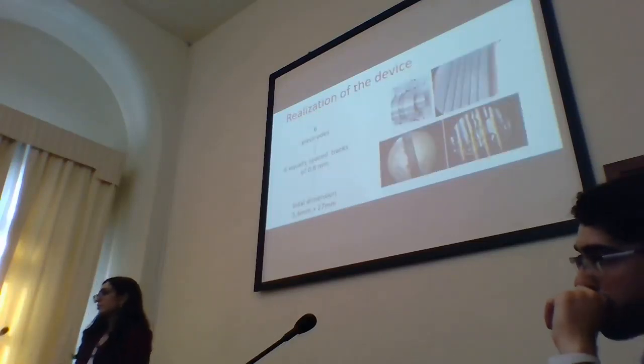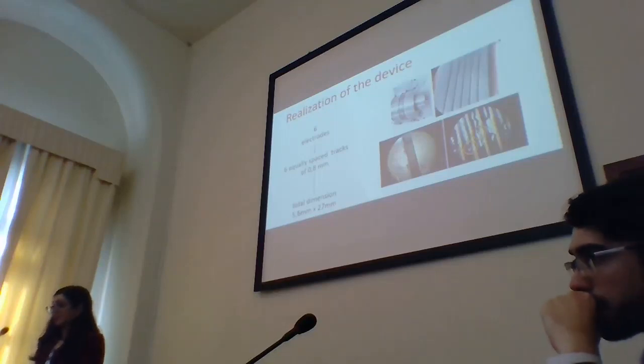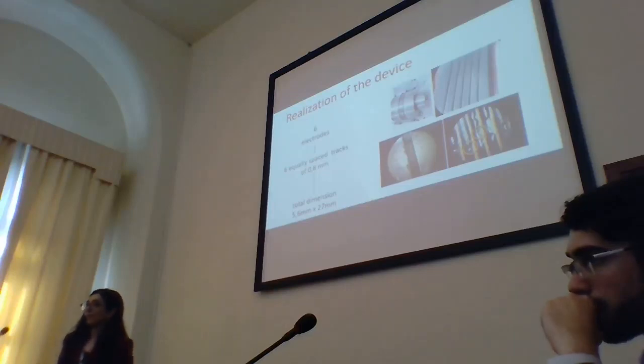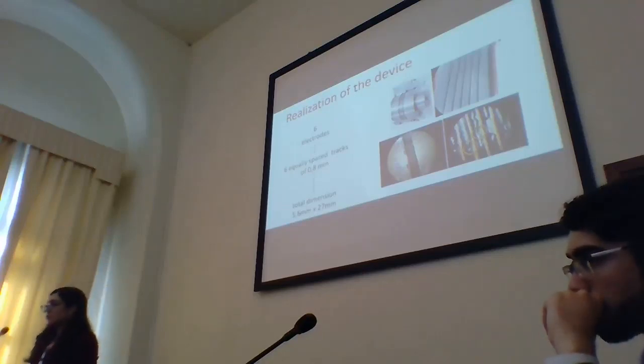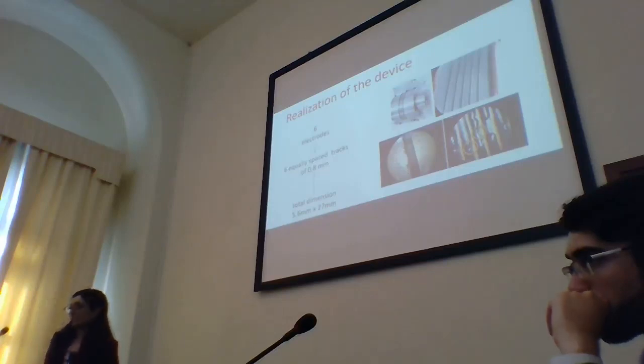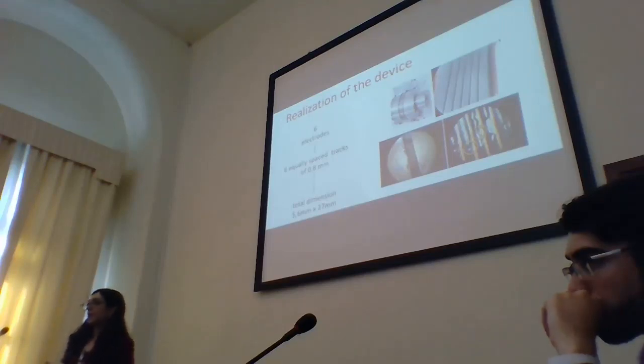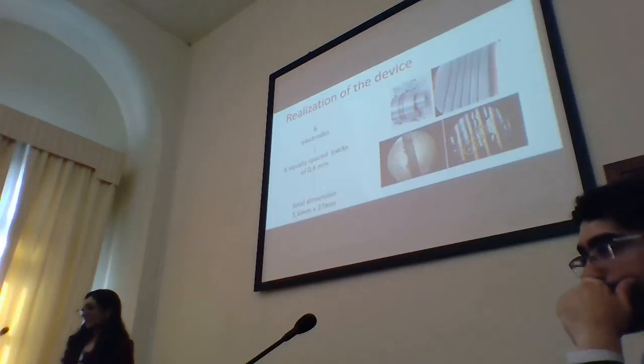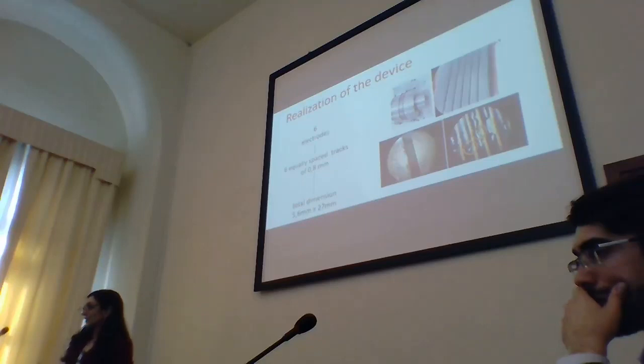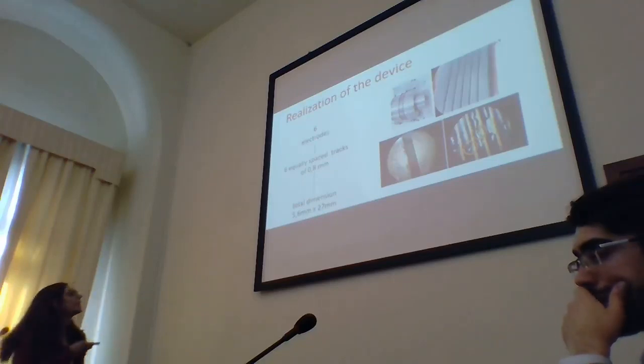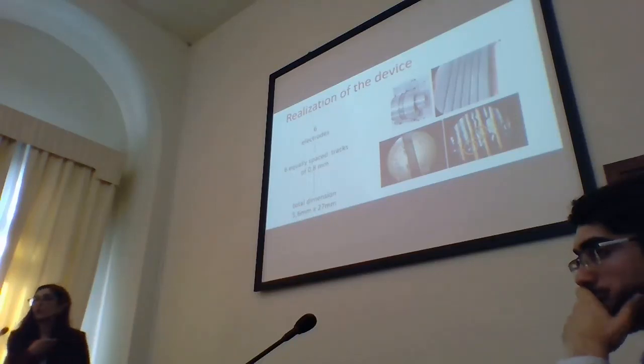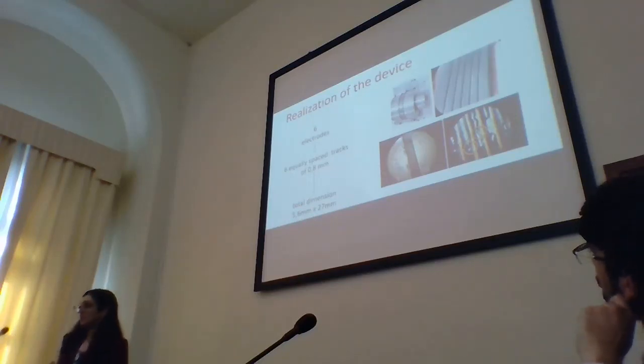I will try to summarize briefly how we realize our devices. First of all, we make 6 or 5 apertures, depending on the number of electrodes that is necessary, with pulsed laser ablation, on a polymeric film, a polyethylene film. After, we put this film on a cylinder, and we cover this film with a stencil, in this case to have 6 tracks of carbon nanotubes. At the center of the cylinder, we have a hole where we put an electrical heater,